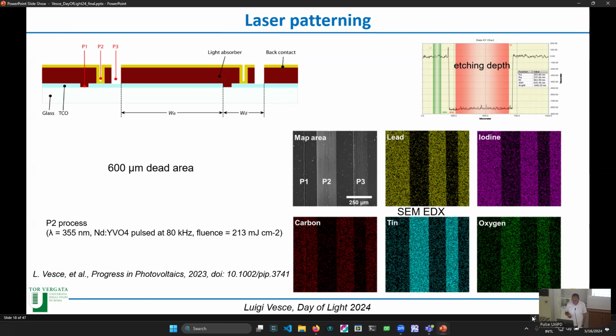For example, if we know the thickness of the stack, the etching depth, so the gap of the trench should be comparable to the thickness of the stack, because we are removing all the stack. And we also conduct some SEM EDX analysis to see if in the trench there are still elements related to the perovskite. We can see that in the P2 trench we remove the lead, the iodine, the carbon, the oxygen. So all the perovskite elements are removed, and just a small signal related to the tin, but it is related to the tin conductive oxide.